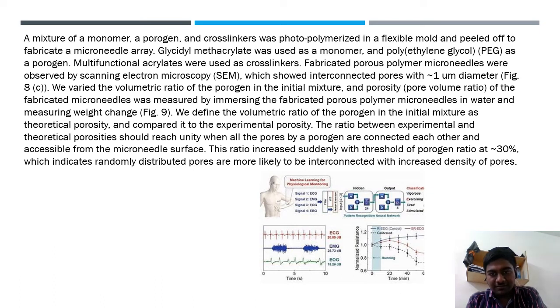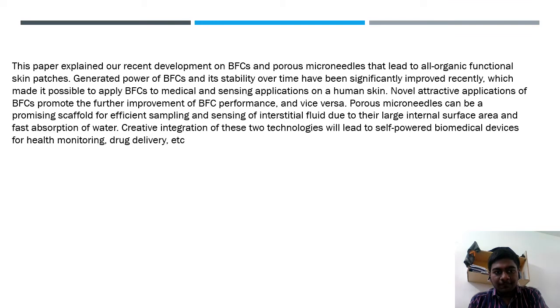This ratio increases suddenly at a threshold porogen ratio of 30%, which indicates randomly distributed pores are more likely to be interconnected with increased density of pores. This paper explained our recent development of BFCs and porous microneedles that led to all-organic functional skin patches. The generated power of BFCs and its stability over time have been significantly improved recently, which made it possible to apply BFCs to medical and sensing applications on human skin.